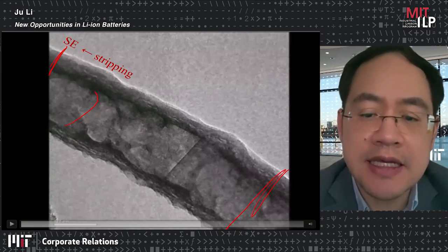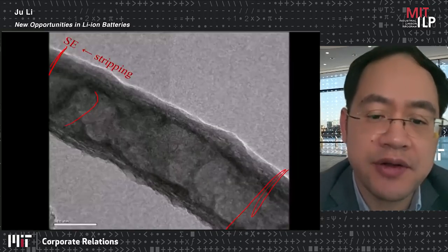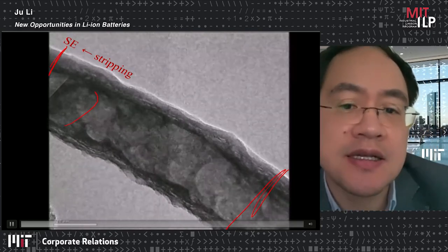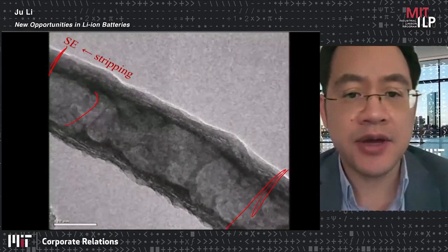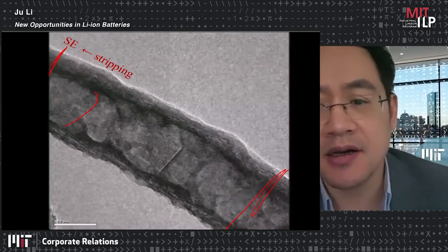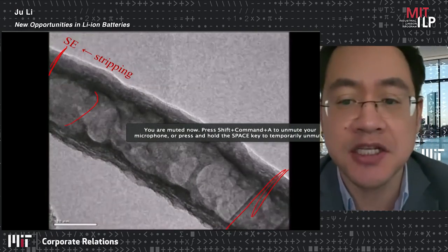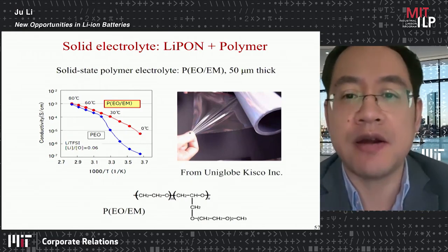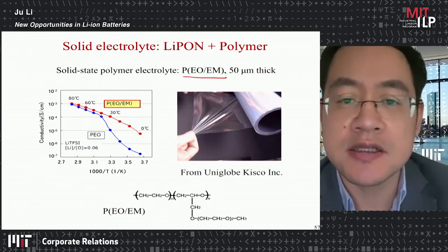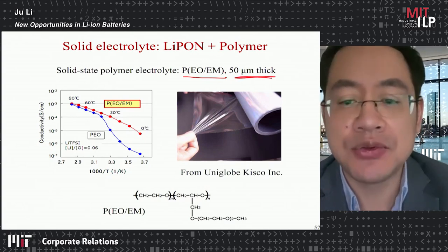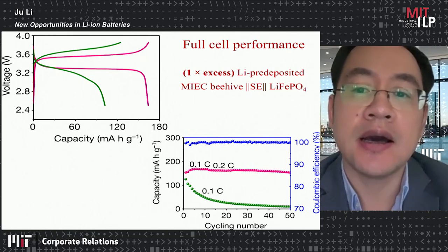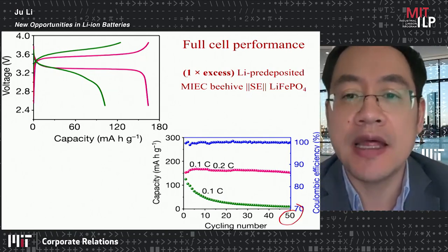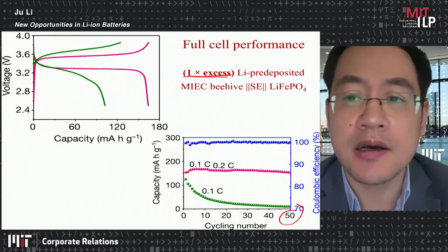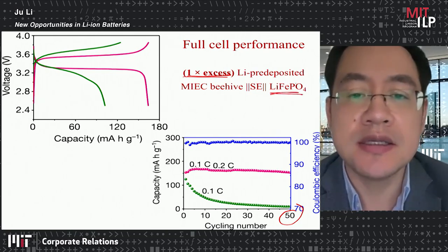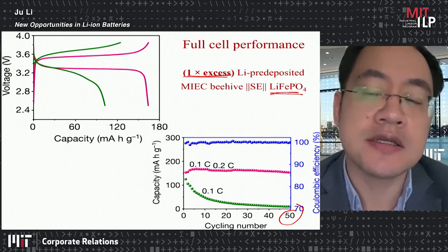You can see, actually, what is very curious is this moved as a single crystal. So this is not a liquid. You can see the faceting. It actually is a single crystal with a specific crystal orientation along the axial direction. In this case, we use still a very primitive polymer solid electrolyte that's actually very thick, and we're able to make an all solid state battery that cycles for 50 cycles with an N/P ratio of one with lithium iron phosphate.